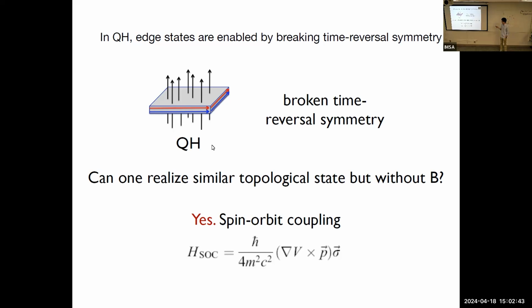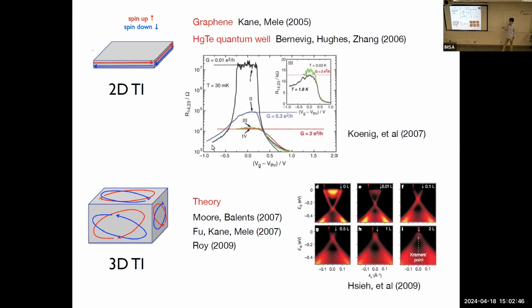And it was first predicted in 2D topological insulators by two different groups. Charles Kane, who was here earlier in this conference, and his group predicted that graphene could host a so-called quantum spin Hall effect. But then it turned out that the value of that spin orbit coupling was too low to be realized in a real material. But the other group, Bernevig, Hughes, and Zhang, predicted that mercury telluride quantum wells could actually host it, and then it was experimentally verified 1 year later, as you see in this figure here.